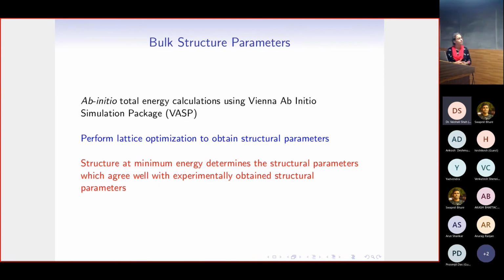So how do we obtain the bulk structure parameters? Okay, we perform what are called total energy calculations, and using this we perform a lattice optimization. Lattice optimization is very simple. All you do is you contract the lattice and you expand the lattice, and for each of these contractions and expansions you have done, you calculate the energy, and then you plot the energy for each of these lattice variations. Then the lattice for which you get the minimum energy is basically the structure that the material likes to be in.